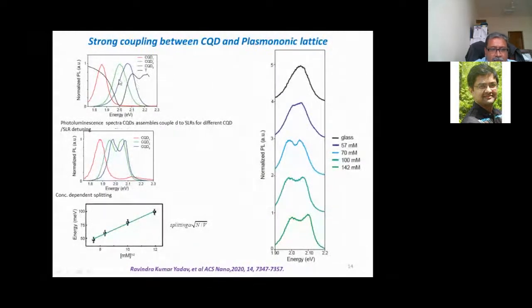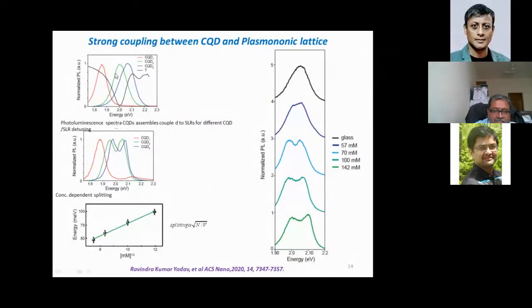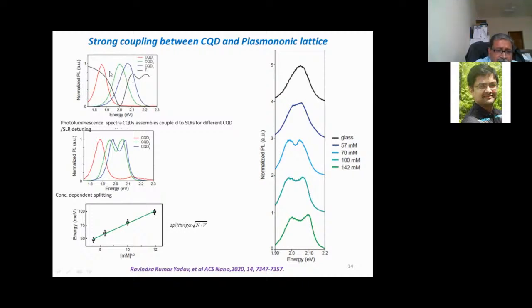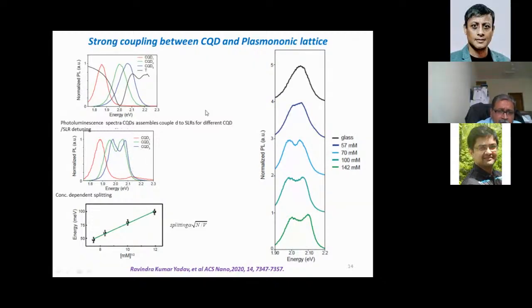The biggest advantage of these quantum dots is that you can tune them spectrally, keeping the material the same. You don't have to do anything to the material, and you can span a fairly large range, in this case almost 250 to 300 meV. This is the lattice resonance, so you can come on resonance or go off resonance, so you can do tuning and detuning. These are then the spectra that you measure on this template for these different quantum dots having different intrinsic spectra. These are measured external to this template.